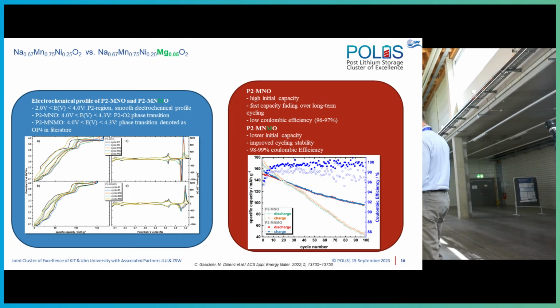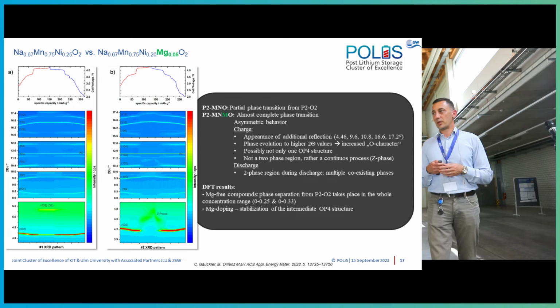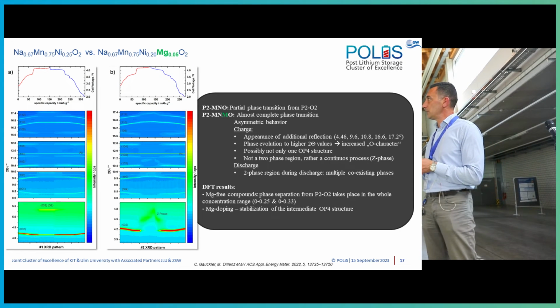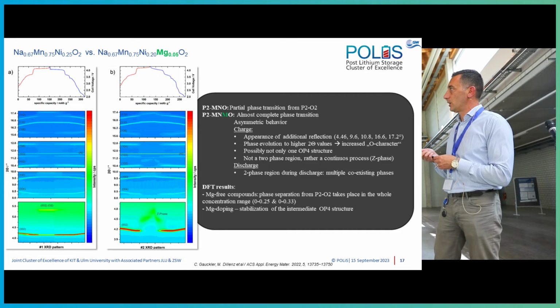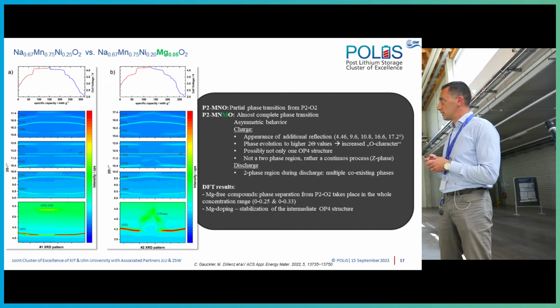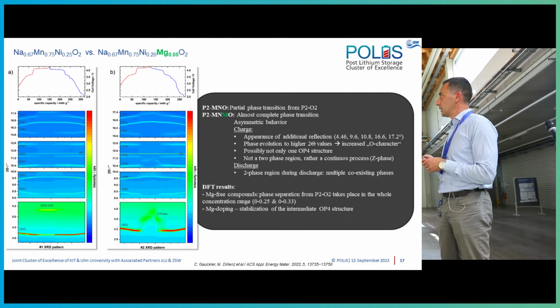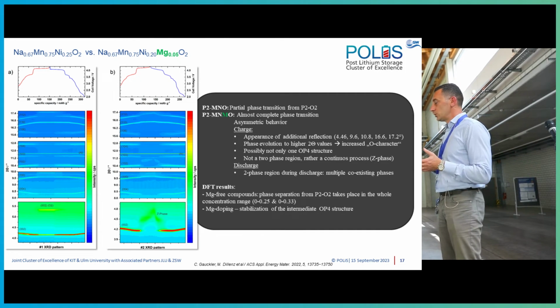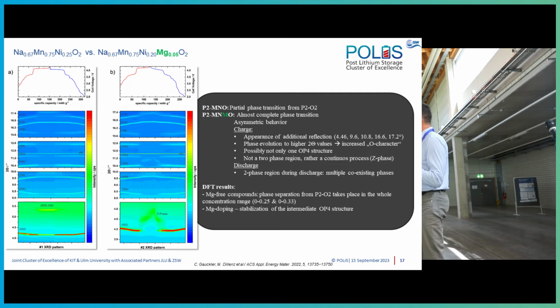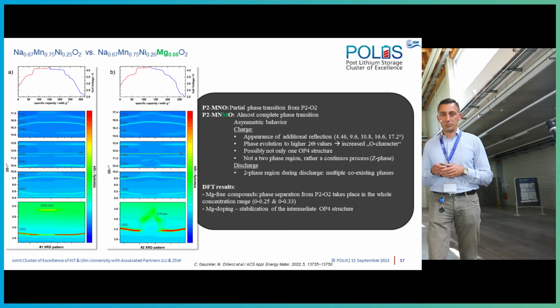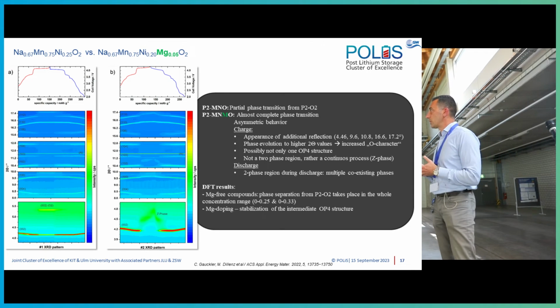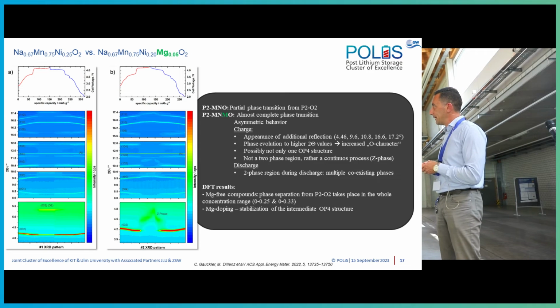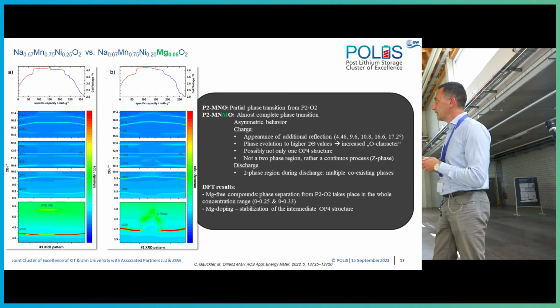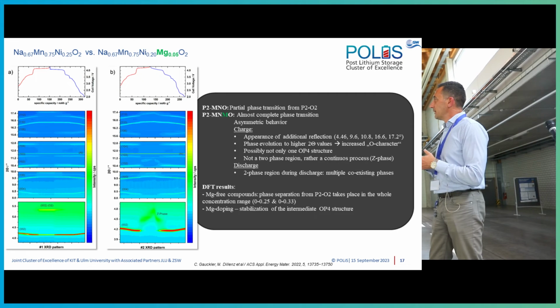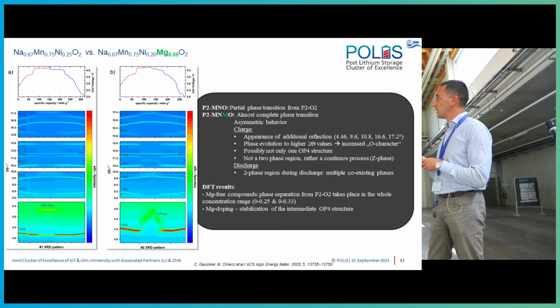We did, as I mentioned earlier, with Sonia, some operando X-ray diffraction for both materials. So on the left, you see the baseline material, and on the right, the magnesium-doped material. For the P2 pure phase undoped material, we have actually a partial phase transition from P2 to O2. This was new for us. We expected to have a full transition. Probably it has to do with the cell capacity not reaching the value that we were looking for.